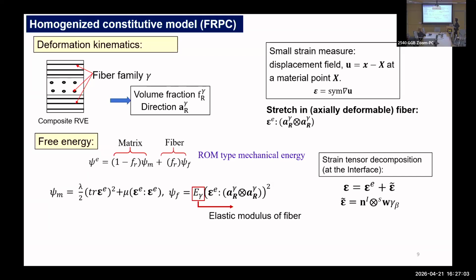So that's the vector representing the direction of the fiber, and this is the fiber volume fraction. In the free energy, it is a very simple rule of mixture, which is factored by the fiber volume fraction. The matrix is considered to be isotropic. The fiber, on the other hand, was an axially deformable, stretch-dominated component. And this is how we calculate the stretch along its direction, and a simple quadratic form was chosen to represent the fiber part of the free energy.